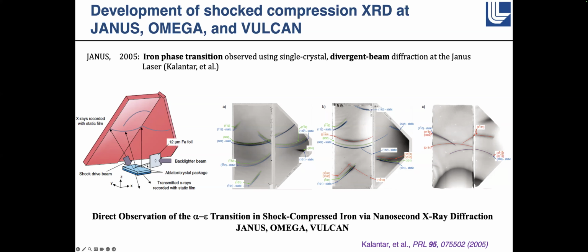But it goes in all directions. And so that gives this diverging beam, and then you put image plates very close to your sample as well. And as a function of angle, you can see the single crystal diffraction. And this shows the data that we obtained. You can see there's a lot of lines here which we identified and were able to analyze what they looked like, and we were able to see as a function of pressure how the alpha epsilon transition in iron occurs.